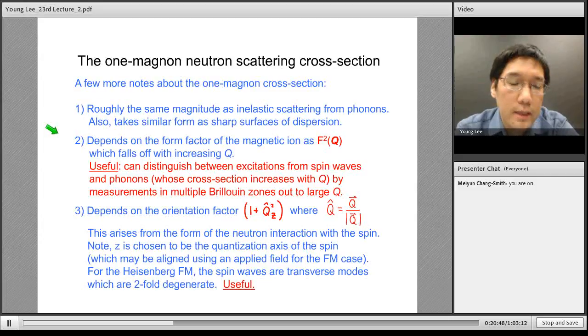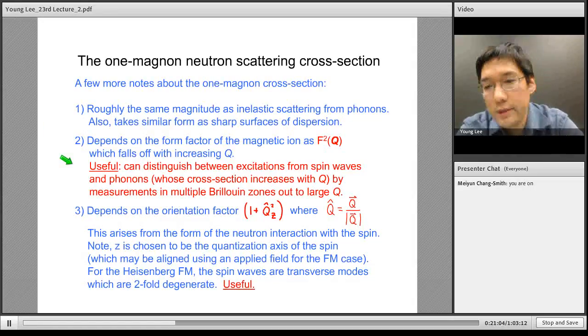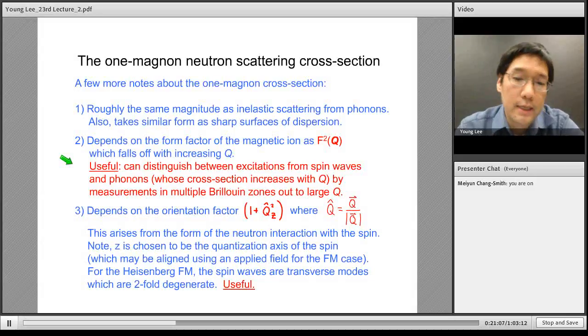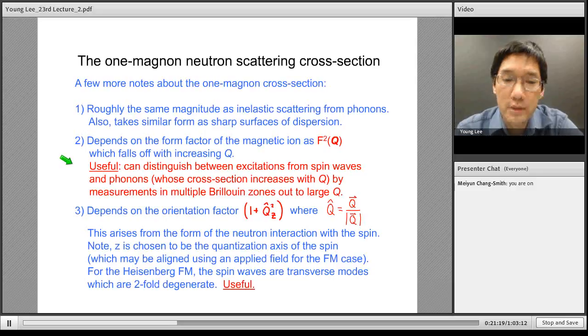But there are some interesting parts of the cross-section, and again, we saw that there's this form factor of the magnetic ion, F squared, which falls off with increasing Q. And this is useful. This is one of the ways that you might differentiate magnetic scattering from spin waves from phonons: if you measure the dispersion relations in several Brillouin zones, and you measure Brillouin zones that are further out in Q, the intensities will change. They will drop off for the magnetic scattering, but for the phonon scattering, they increase with Q. So by looking at how the intensity changes with Q, you can have a better idea of what you're seeing as phonon or magnon.